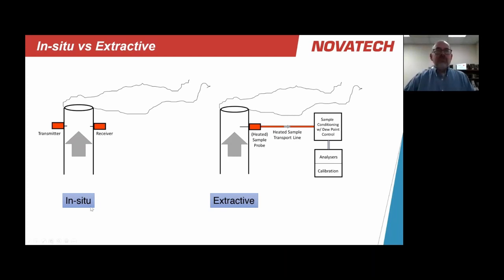When we say in situ, the analyzer is mounted directly on the process. And I'm showing a chimney here for argument's sake. It doesn't have to be that. It can be a pipe. It can be a vessel. It doesn't really matter. But in situ measurements are done directly on the process. Extractive measurements, as the name implies, pull a portion of the sample, bring it to a sample conditioning system that then introduces them into the analyzer. And this is where the big difference between these two lies.